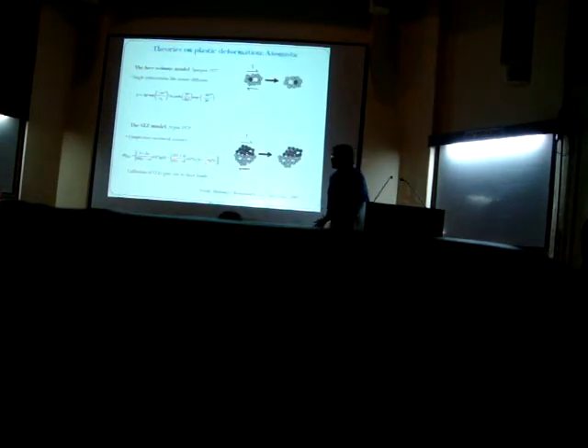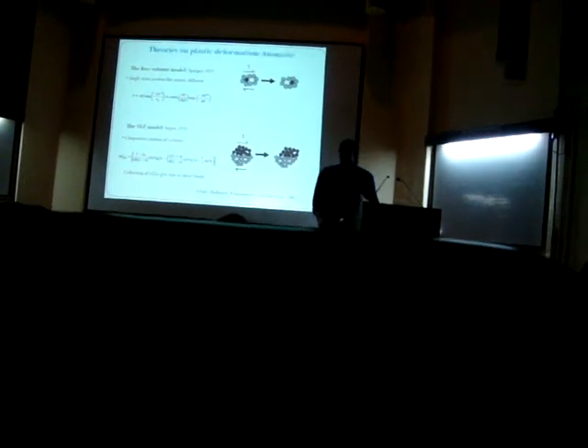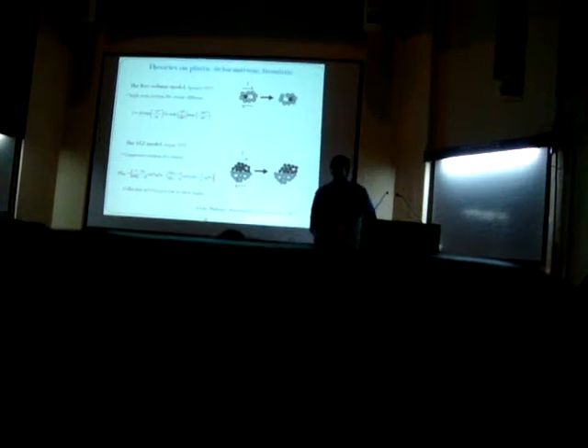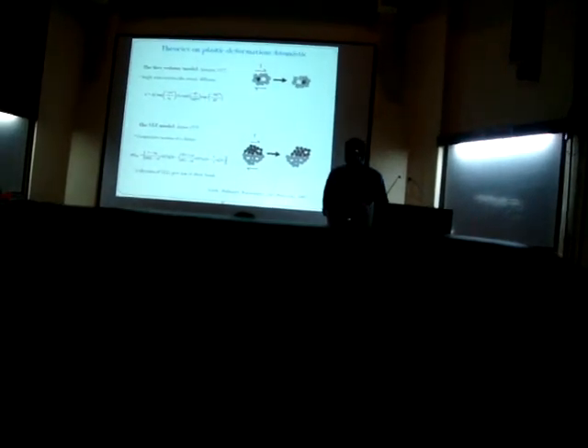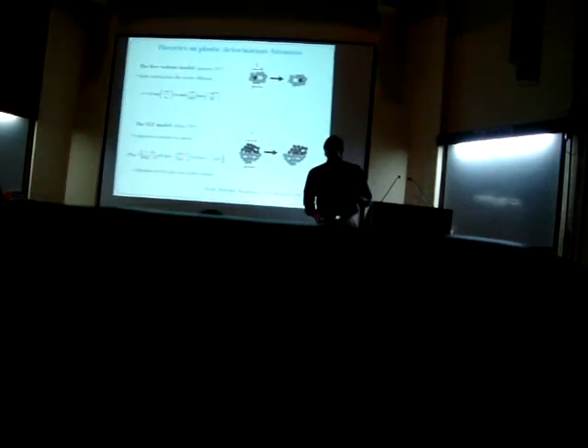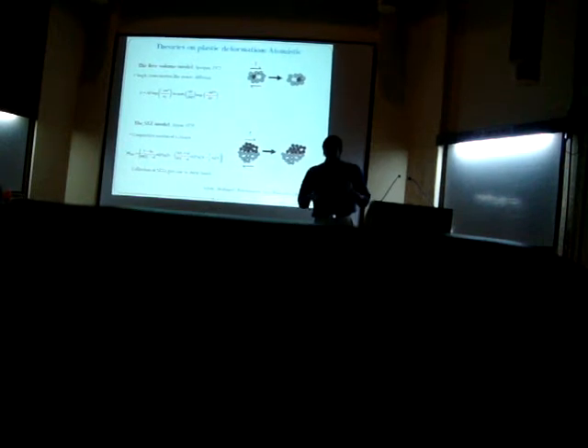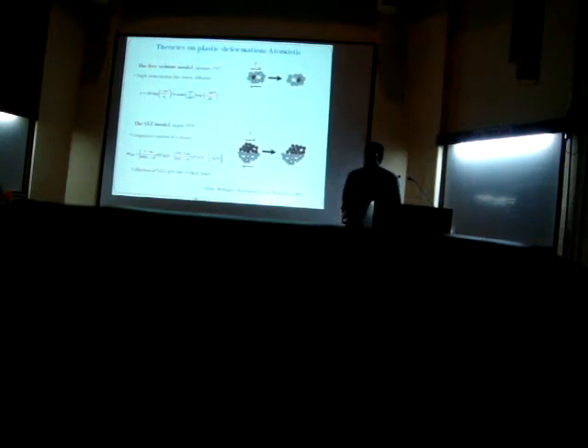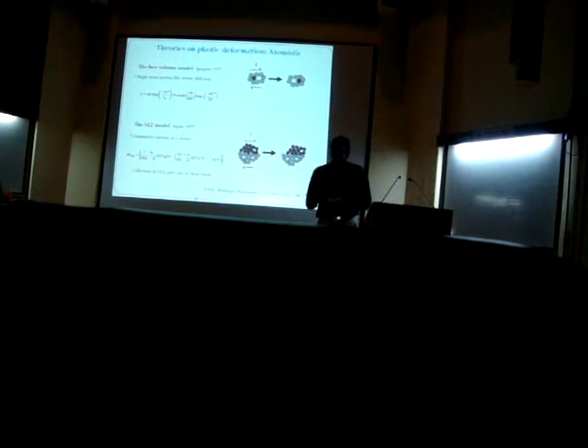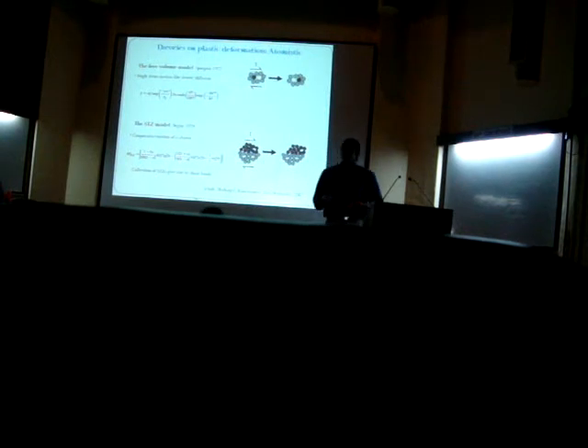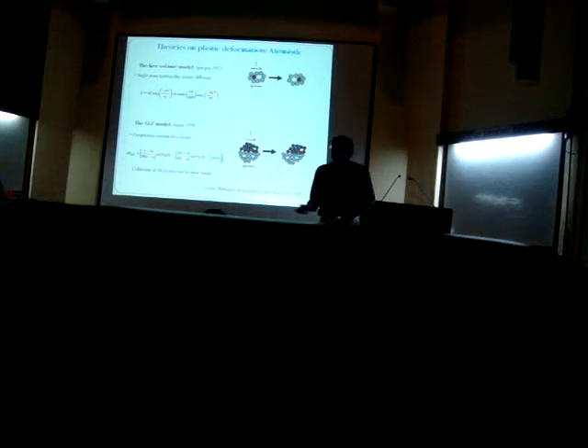Now, theories of plastic deformation, I would briefly talk about, from the 1970s to 2000 to the present. There are some four theories which have been proposed. Some are based on the fact that the phenomenological aspect of glasses is very similar to diffusion. So the movement of atoms from one place to another under shear can also be described as a diffusive process, which is what Frank Spaepen first did in 1977, and he was able to map this to the deformation of glasses in different strain rate and different temperature regimes. He was able to make a deformation map.